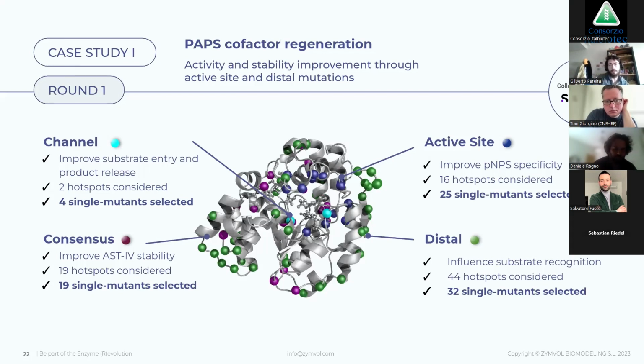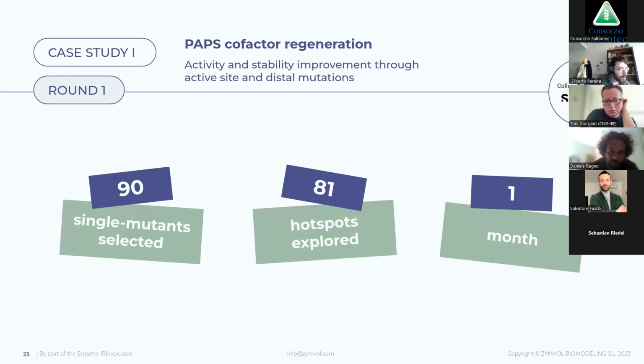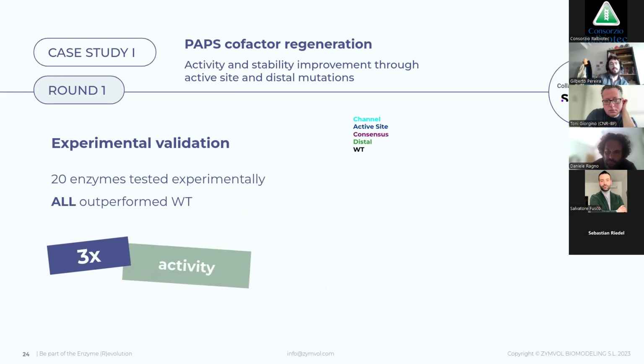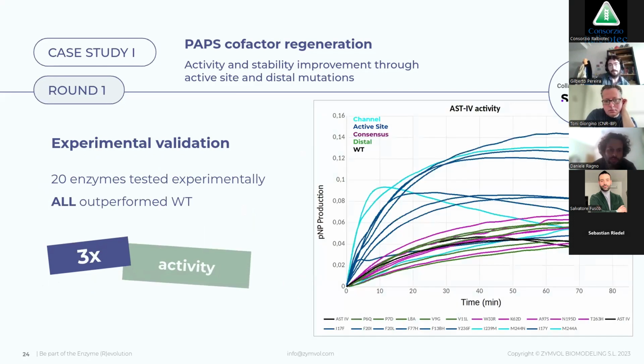We ended up with about 90 mutants, exploring 81 hotspots in 1 month for the first cycle. We tested only 20 of these enzymes, but found that many of them were more active than the original enzyme.